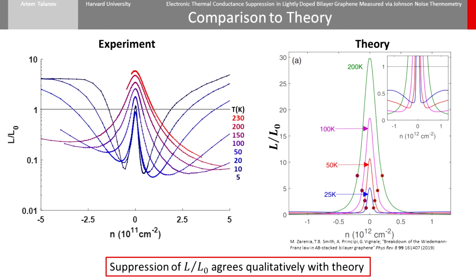If we look at the inside of the theoretical plot, we see we have rather good qualitative agreement for the suppression, at least before the ballistic type enhancement starts masking the true Lorentz ratio. It's unclear why our measured suppression is so much stronger than the enhancement. It's possible that the graphite gate is too close to the bilayer graphene at about 8 nanometers and creates some screening, and that a yet cleaner device would show a stronger enhancement. We are currently working on fabrication of more devices.